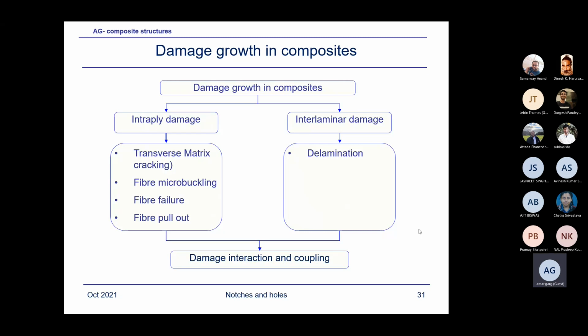You will generate the effect of various parameters using the finite element method, validate the finite element method with the test data using some coupons, element tests, or panels, and generate some kind of surface parametric analysis using some linear programming. There are standard programs available. And then using those programs, you will generate some kind of empirical equations. And that is what is used by the industry. Empirical equations developed using finite element method and test data to analyze the structures.